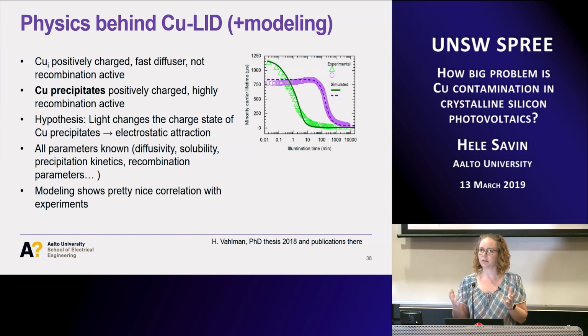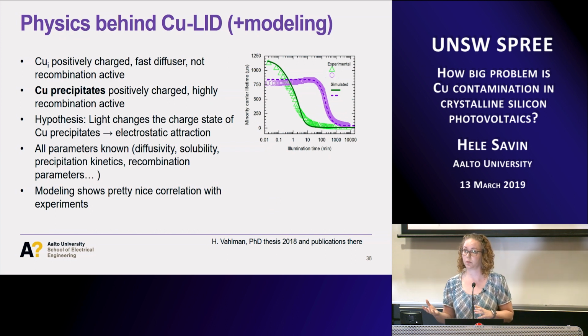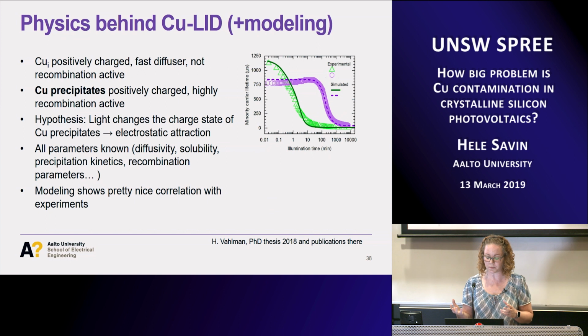And to model this kind of defect reaction is relatively simple, because we know the parameters for this kind of reaction. We have copper diffusivity and solubility in the literature. We know the metal precipitation kinetics, and we know the recombination parameters for the copper precipitates. And indeed, I think modeling shows a pretty nice correlation with this theory, so we are quite convinced that this is what happens.